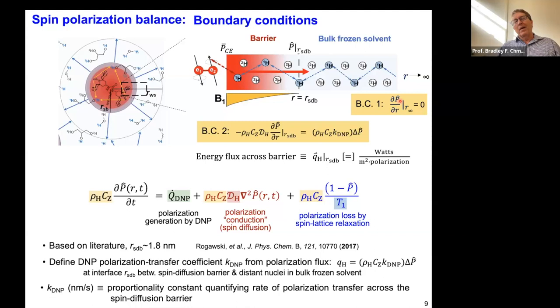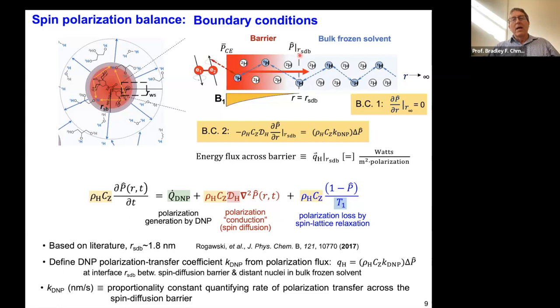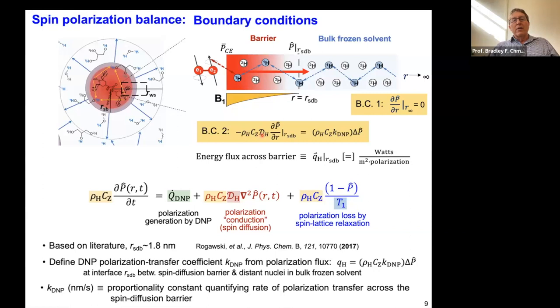The first boundary condition in the frozen solvent: very far from a paramagnetic center, the derivative of that polarization approaches asymptotically zero — a symmetry boundary condition far from the paramagnetic center. We also have a boundary at the spin diffusion barrier, and that's really where the challenge is. How do you characterize that? It's not easy. That polarization at the thermal boundary begins, and this is the same problem in heat and mass transfer — we don't know what the concentration is very near the film resistance to mass or energy transport.